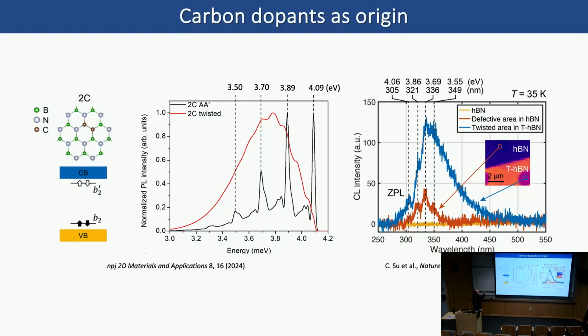There's another project. We're trying to see whether we could bring the emission of a monolayer defect to be bright. Actually, we found some pretty tricky ways of doing it. We're still exploring it, but there is pretty good progress to bring those monolayer defects and let them emit light. So yeah, there are trade-offs between monolayer and bulk material. Bulk actually buries all the defects inside, which makes it more stable. So that's the advantage of bulk.